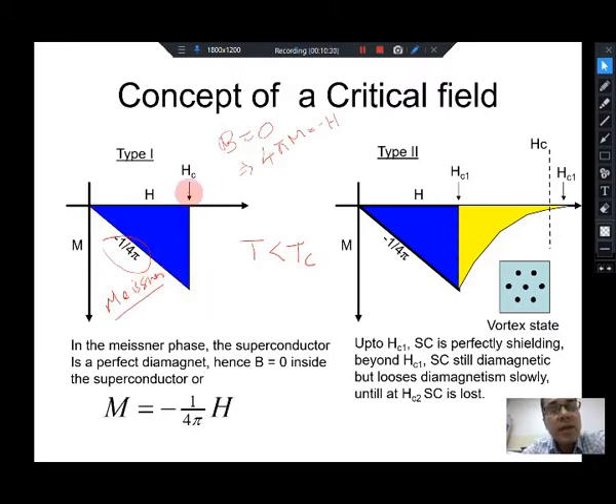However, can you indefinitely keep on applying a magnetic field and measuring this Meissner response? No. There is a critical field Hc above which the magnetization sharply drops to 0, and from a superconducting state the material becomes normal. Even though your temperature is less than Tc, if you apply a magnetic field, you take the superconductor, you measure its magnetization, the susceptibility will be minus 1 by 4 pi, and it will be superconducting until this thermodynamic critical field value. If you cross it, the magnetization crashes and becomes zero and the material turns normal although your temperature is less than Tc. This is the measure of your thermodynamic critical field.